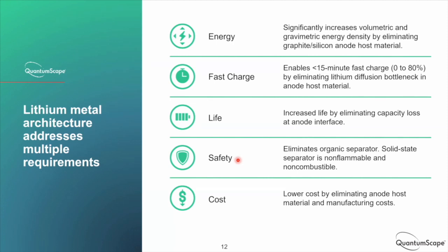So this is why most modern separators today will start to include a layer of some ceramic particles that are still porous. The purpose of those ceramic particles is to try and prevent this thermal runaway by putting something that won't melt in between the anode and cathode. Well, our separator is this entirely dense ceramic material. So I think we achieve that effect, hopefully to a greater extent. And then in terms of cost, as I've described, we eliminate the anode manufacturing step and materials. So hopefully we can lower costs as well. So this change, we hope to address these five metrics simultaneously.